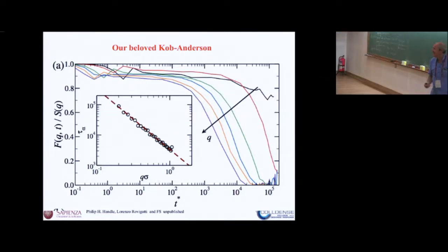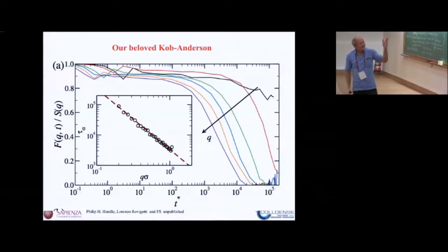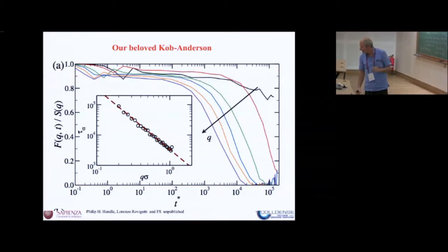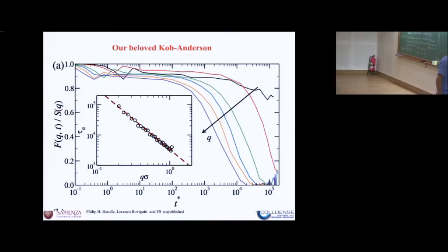This is our beloved Kob-Anderson model, right? You cannot miss it. The Q vector dependence for this is Q square. And it comes from the fact that now you don't have only to decorrelate the density, but you also have to decorrelate the relative concentration of the particle. This is a binary mixture.